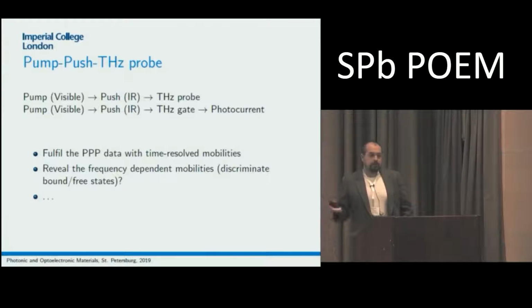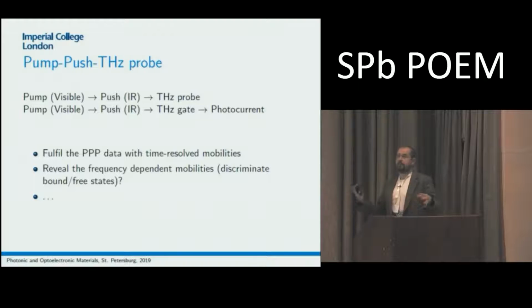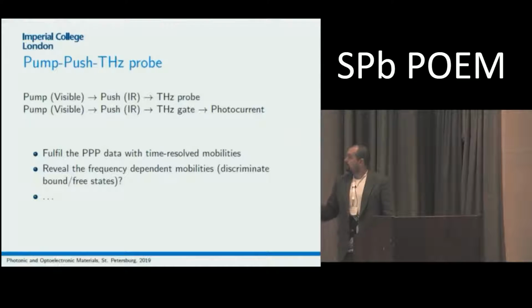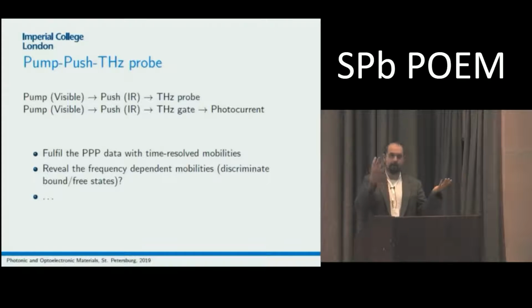So what can be done further is that, since we have this setup and these facilities, we can do a visible pump, then push and probe with terahertz to measure directly. As we already have the information on concentration, we can also study the mobility of carriers directly and compare optical probing with terahertz probing. And we can turn to photocurrent measurement gated by terahertz radiation. So we have the pump, then we have the terahertz field applied and gate with the terahertz pulse and measure the photocurrent from the photovoltaic cells directly. And look into terahertz frequency-dependent time constants in carrier decay processes, and thus understand a little bit more about hot carrier dynamics in these materials.